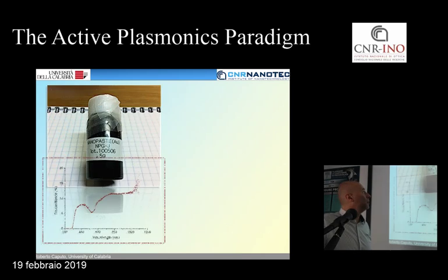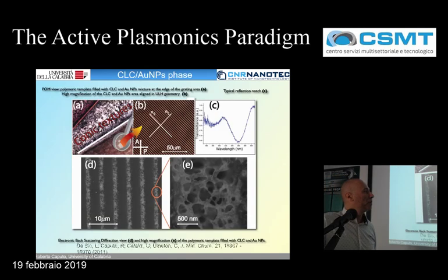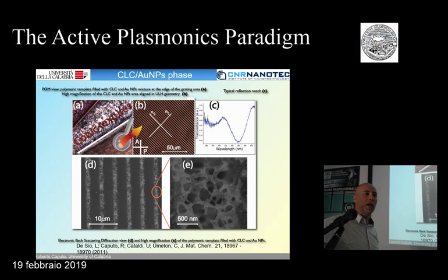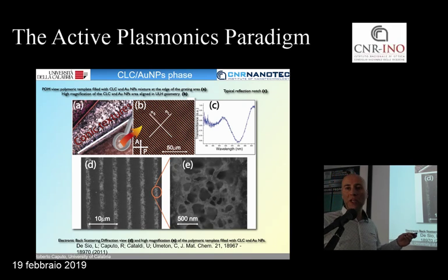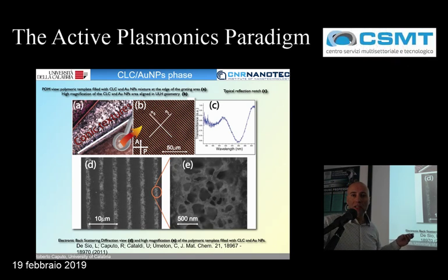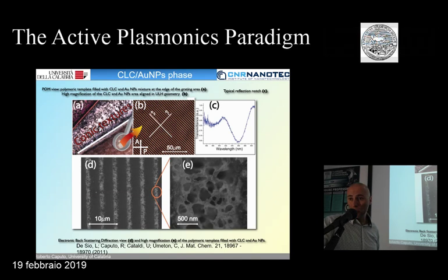So we elaborated a procedure for washing away the original liquid crystal by solvent, and we succeeded because indeed you are able to get a polymeric template that you can afterwards fill in with the liquid crystal doped with the nanoparticles. So the first experiments were made with the cholesteric liquid crystals, which have a particular organization, like helicoidal organization. And we doped this material with nanoparticles.